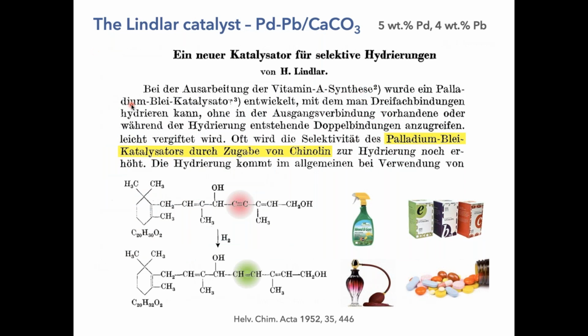If we go to another long-standing example of a very successful catalyst, that's the Lindlar catalyst for stereo and chemoselective hydrogenation of alkynes. So very complex molecules, and you want to hydrogenate a triple bond into a double bond. And the prototypical catalyst is a palladium lead catalyst. So the palladium catalyst is heavily poisoned by lead and also by quinoline in order to make it selective.